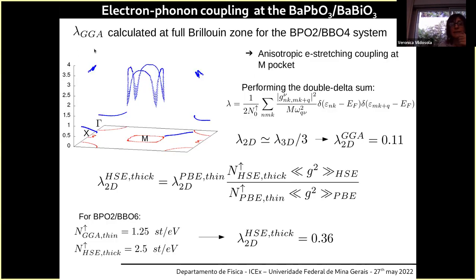Then we calculate the complete lambda along the full Brillouin zone. We observe that there is some anisotropic electron stretching coupling at the M pocket. We obtain at the level of GGA a lambda of 0.1. And then we calculate how this value changes with HSE. We were not able to do this lambda calculation on the full Brillouin zone with the hybrid functional. But what we did was to rescale the value obtained by GGA or PBE with these factors. We divided by the density of states obtained with GGA, and we multiply by the one that we obtained with HSE. And we did the same with the matrix elements.